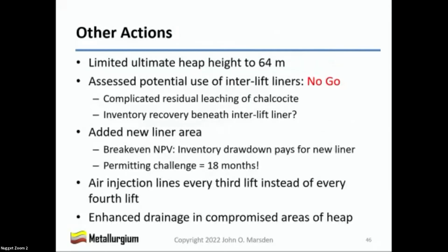Next slide, please. So what did he do? So for hydraulic conductivity, he remained concerned that he might have problems at heap heights above 60 meters. An engineering company that he hired suggested that he look at installing interlift liners in the heap between lifts 5 and 6. Didn't take him long to figure out that that wouldn't work for a secondary copper sulfide leach when the residual copper recovery from buried lifts is so crucial to overall recovery. Also, no one within the engineering company could tell him how he would recover the copper in solution inventory beneath the liner. So that was a no-go.